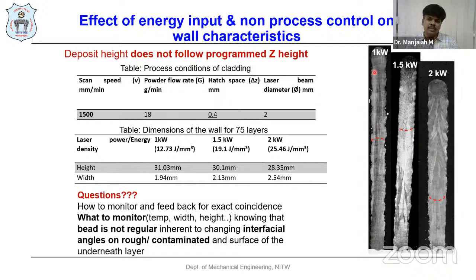Because we have to optimize the laser power or the energy density. If you see 1 kilowatt, 1.5, 2 kilowatt, you can see these three representations to express how much layer width and height has been in each layer. For example, 75 layers were deposited.